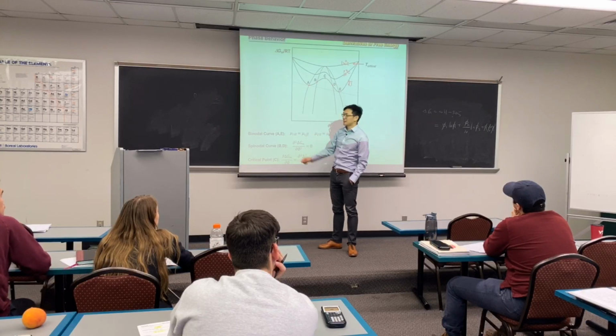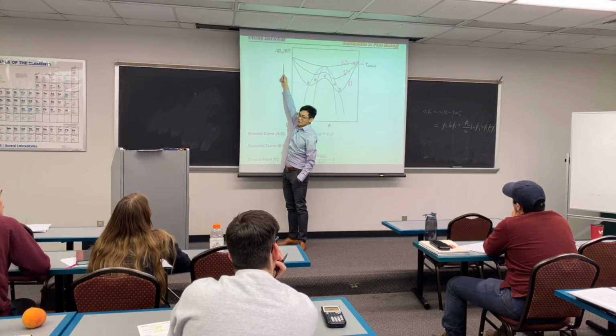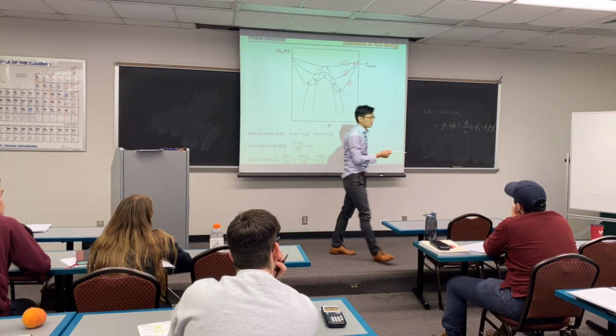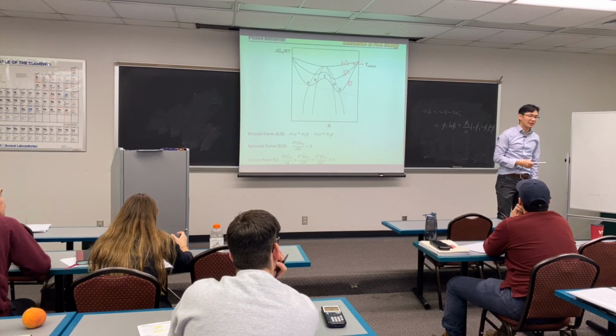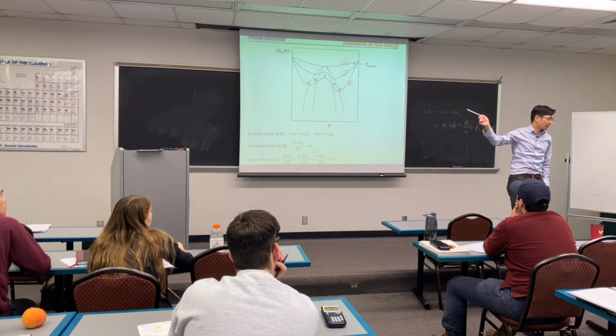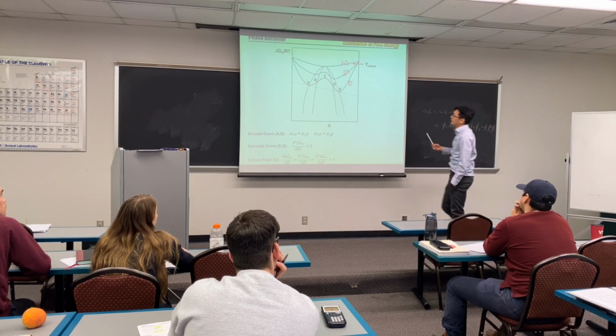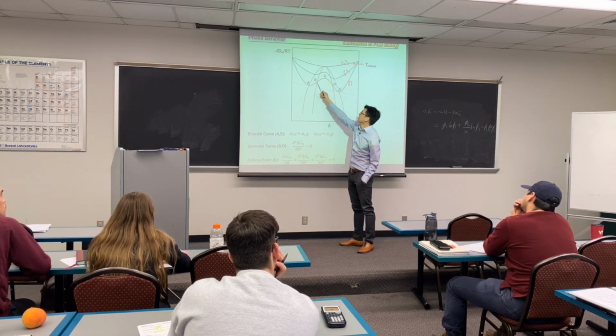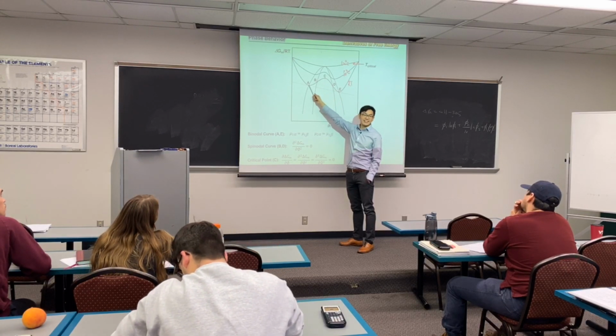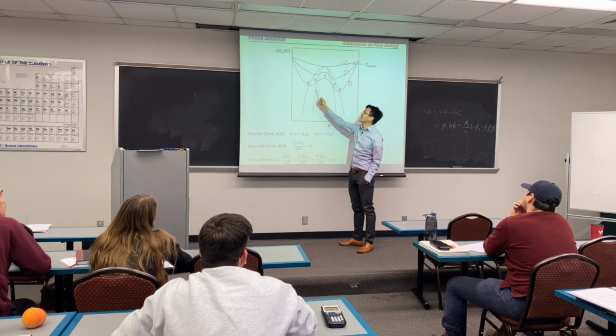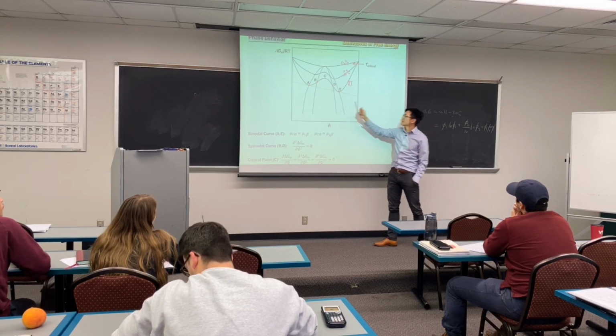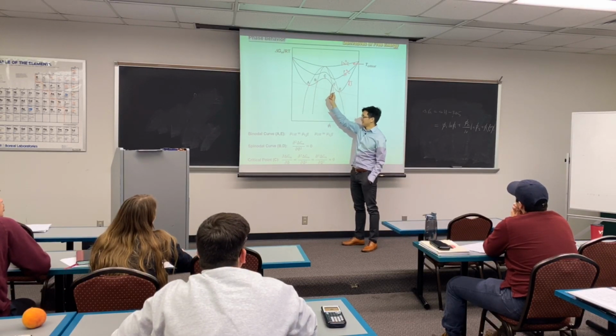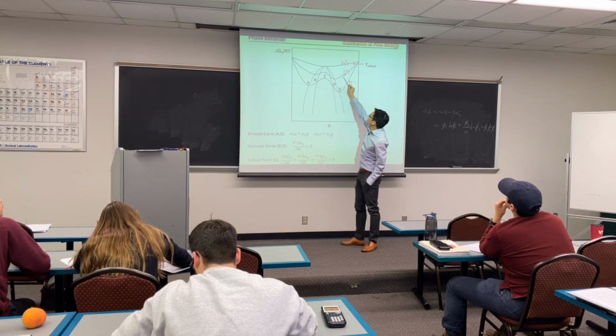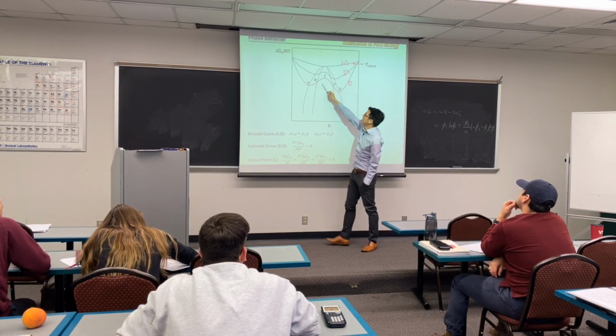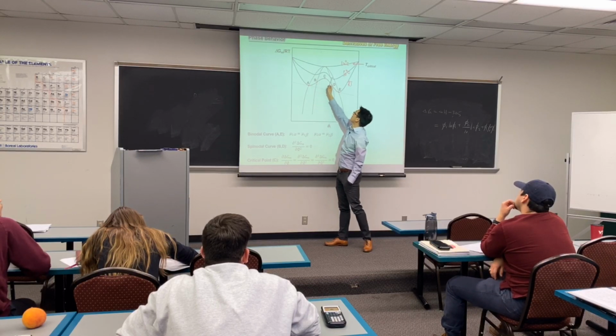And please pay very important attention. This is plotting delta G. And the question back to you, how do we get the phase diagram? We basically get it from the delta G curve. At each temperature, you would have data points A, B, C, D, E. A and E are binodal. How about B and D? Spinodal. And you have critical points, which should not shift. So now at a different temperature, at 50 degrees, again you would have the same A, B, C, D, E right here.